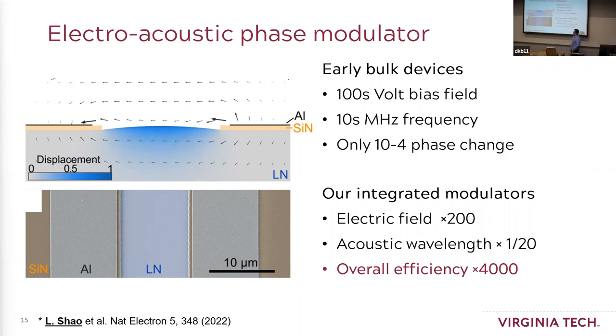Second thing is about acoustic wavelengths. Previously we had 10 megahertz. Now we can go to 2 gigahertz, which is over 20 times smaller. And if the wavelength is smaller, it has a higher phase change per period, and the device also gets shorter, so it's improved. Taking those two together, overall we have an efficiency improvement of over 3 orders of magnitude. If you multiply 10 to the minus 4 by these 3 orders of magnitude of improvement, it's very close to 1. That becomes something we can make useful.